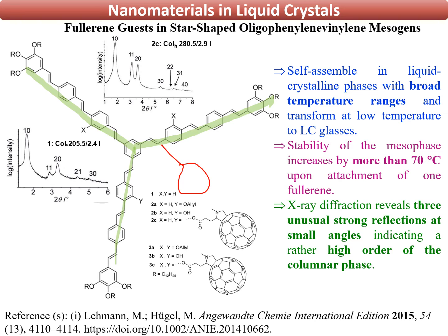Our first example of nanomaterials in liquid crystals is fullerene as a guest molecule in a star-shaped oligophenylene vinylene mesogen. This star-shaped OPV is responsible for discotic mesophase formation. In this work, a fullerene molecule is covalently linked to one arm of the star-shaped OPV. It is observed that on attaching one fullerene molecule, the stability of the mesophase increased by more than 70 degrees Celsius.